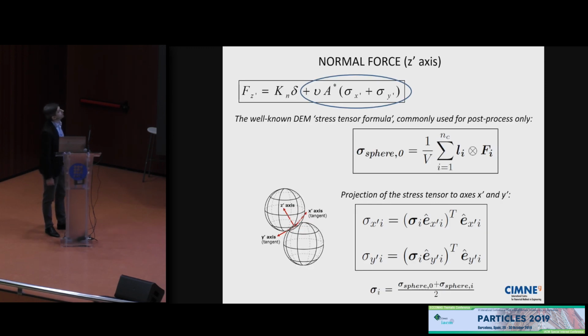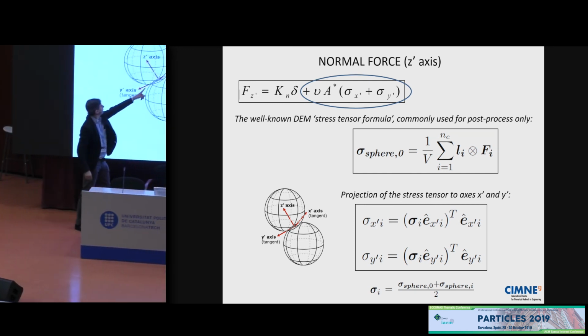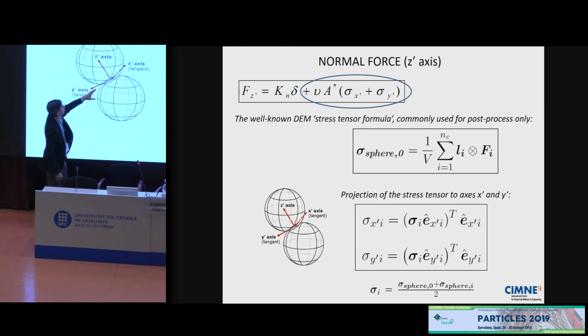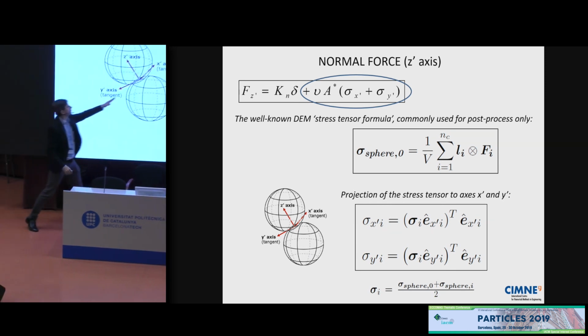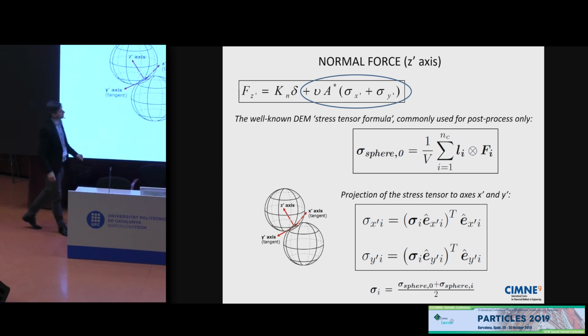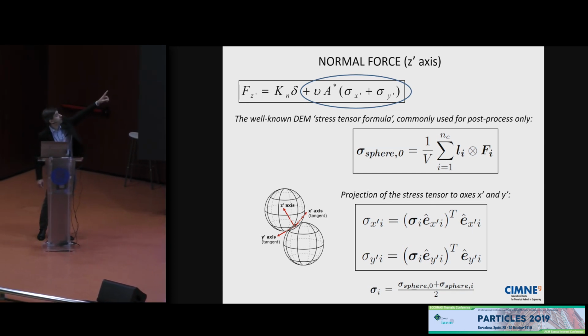And how can we fill that term? Well, the stresses are known. I mean, traditionally in the DEM, they have been used to plot results. We have seen many talks in the previous particles conferences, where people draw the stresses. So our idea was to use those stresses to feed that term. And of course, you have to project it, because you have to add the stress in this direction and the stress in this direction. So the global stress tensor, you have to project it to these directions using these formulas. That's only a projection in those directions. So you can fit the extra term that you have on top.